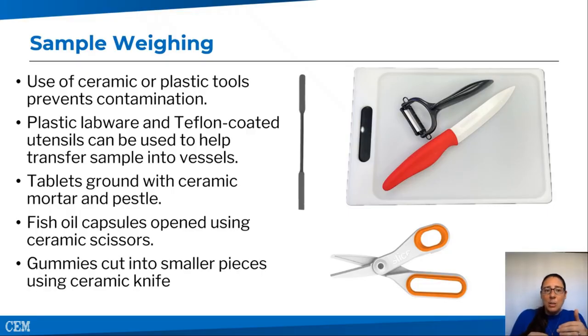You need to be using ceramic and Teflon coated options, and they're out there, right? You can see some pictured on the screen here. How you're interfacing with that sample, how you're getting that into your vessel really matters. Also, we talked about needing a homogeneous sample, and that's really important as well. It's hard to get a homogeneous sample of a gummy, so you may need to grind your sample or cut it up into very small pieces. And just think about when you're doing that, that you're again going back to using ceramic or Teflon coated components that are not going to add any contamination, but also help us achieve a homogeneous sample the best that we can.